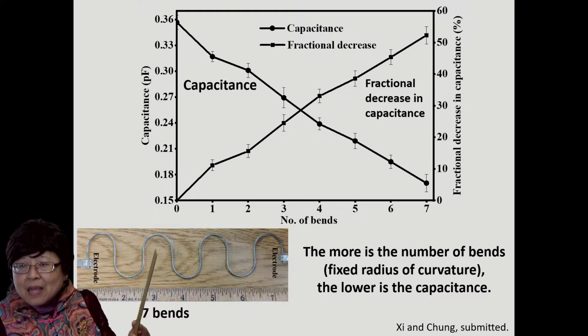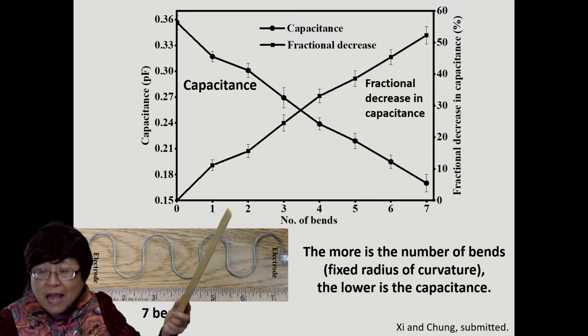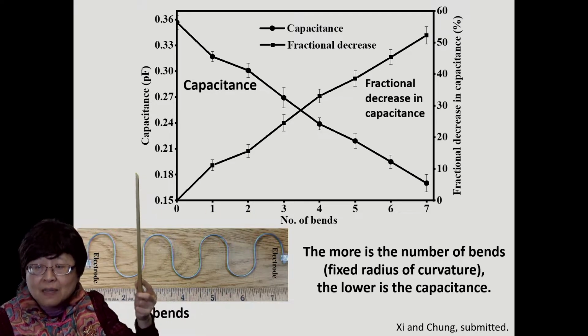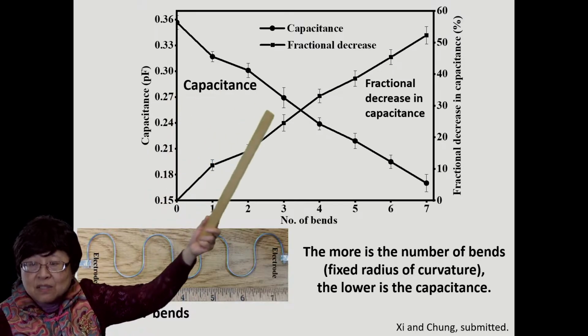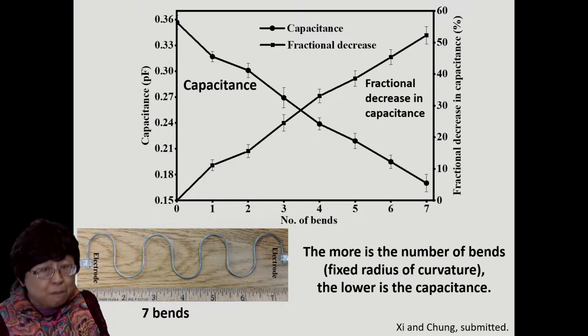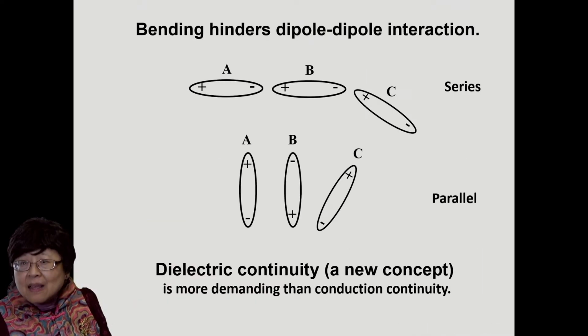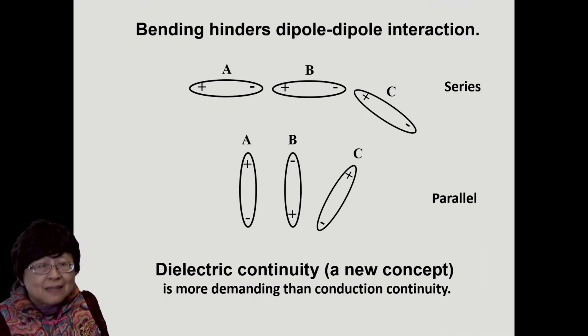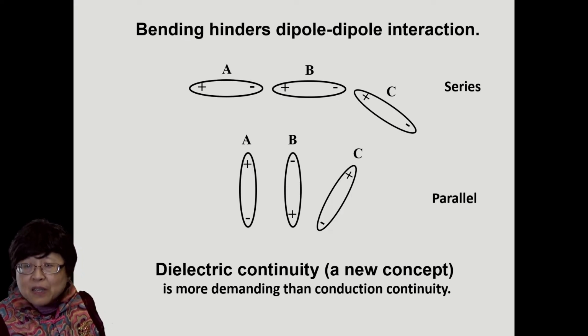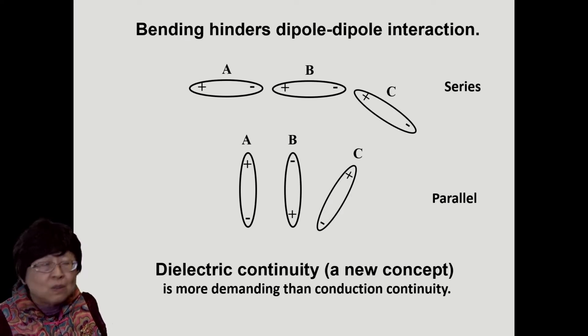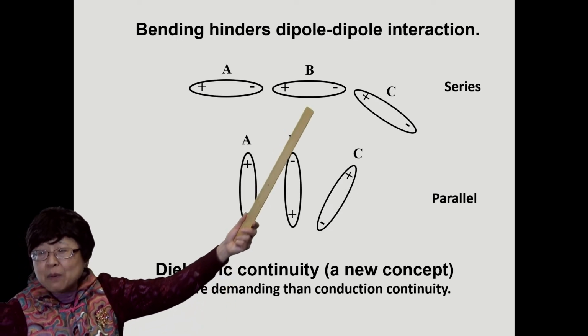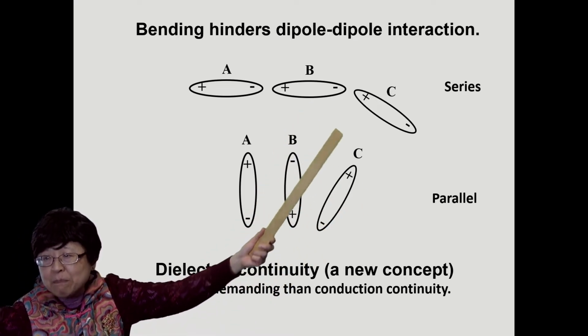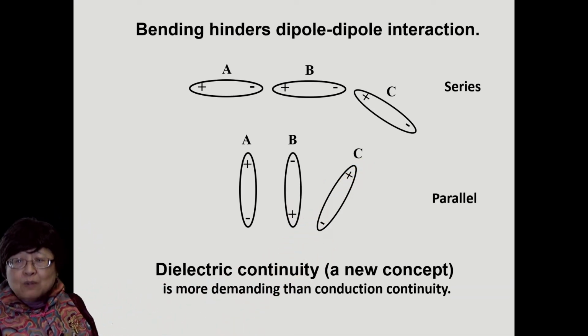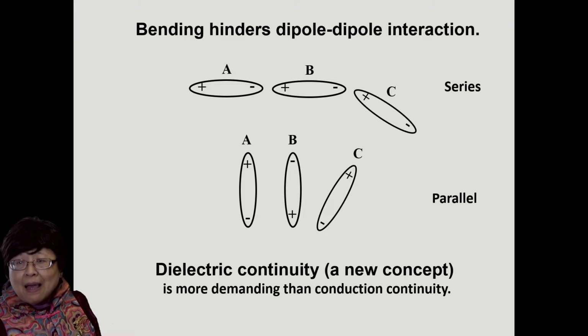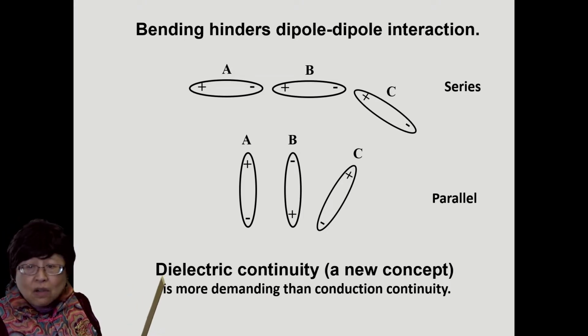Okay. And one can instead look at the effect of the number of bends at the same radius of curvature on the capacitance. And again, we find that the capacitance decreases with increasing number of bends. Why is that so? Why does the bending decrease the capacitance? That is because the bending hinders the dipole-dipole interaction. Whether you consider dipoles in series or dipoles in parallel, when you have a bend, you would have less dipole-dipole interaction across that bend, and that means less dielectric continuity.